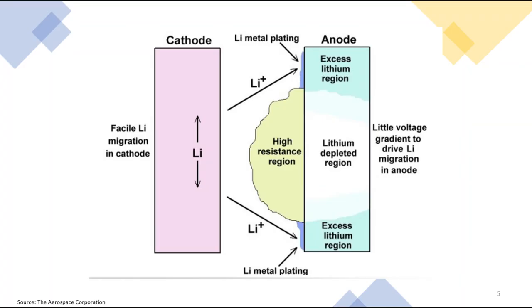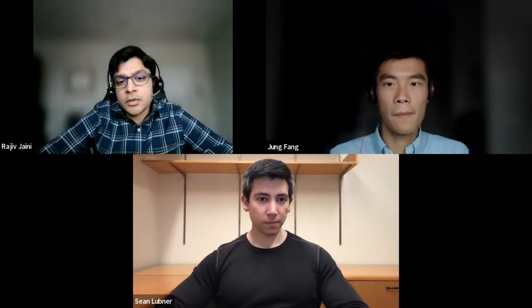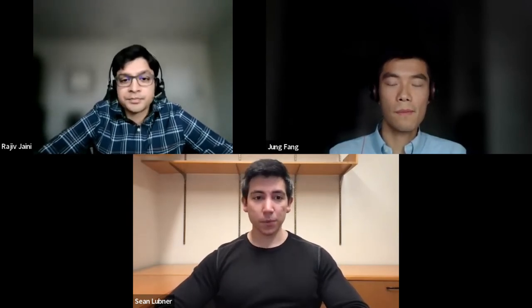So to follow up there, there are concerns with lithium plating that might happen, particularly during fast charging. It seems like there's a balance here between some of the thermal effects that you're talking about, basically heat being trapped within an element of the cell, and lithium plating. Did you see anything in your work regarding lithium plating? Yeah, exactly, so you're right. I kept saying heat getting trapped is one of the barriers to overcome. Lithium plating very much is another big one.